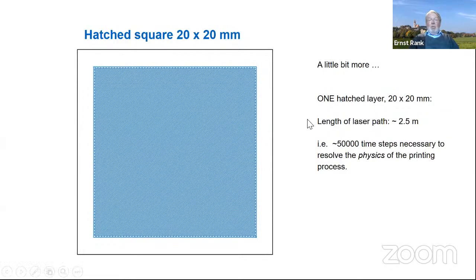So let's look at this square, which is hatched, again 20 by 20 millimeters, and the enlarged part shows the scan strategy of the laser. It starts in the corner and then goes to and fro in the diagonal direction of this square. We already have, for this very simple problem, and again it is only one layer, a laser path length of about 2.5 meters, meaning that we need 50,000 time steps if we really want to resolve the physics on the scale of the melting pool.